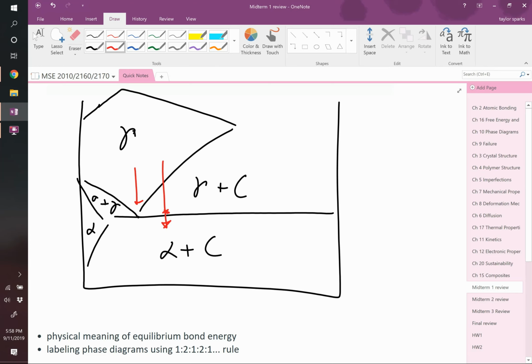Is the microstructure always formed when it goes from a liquid to a solid, or from one solid to a different solid? So no, not necessarily. In this one, we never heat it up to a liquid. When you process steel, the temperature to melt it entirely is really, really high. So you might just heat it up all in the solid state. You might heat it up to this austenite region, let it sit there until it's all austenite, so you've got a bunch of grains of austenite, and then you cool it down. And depending on it, maybe when it's up in that state, you add or remove carbon.